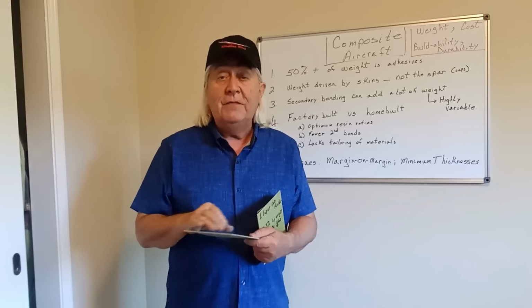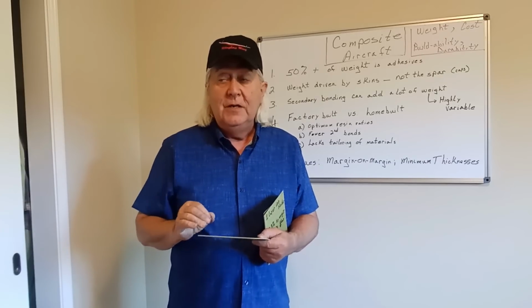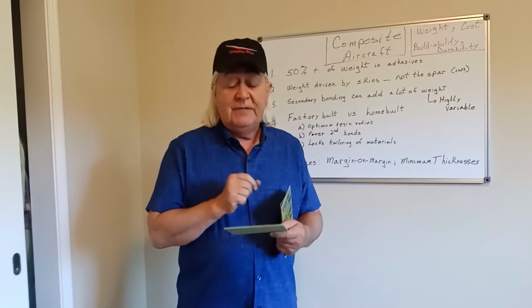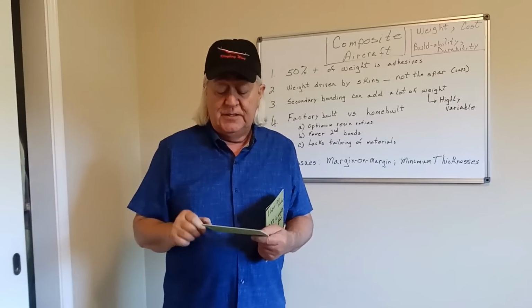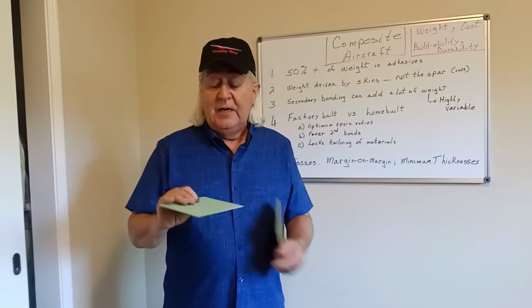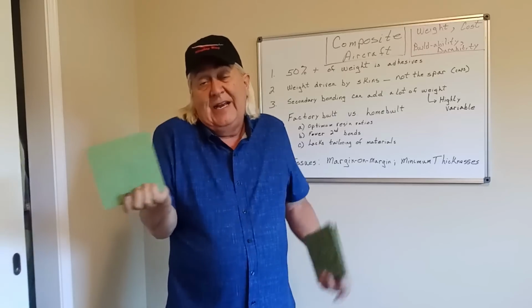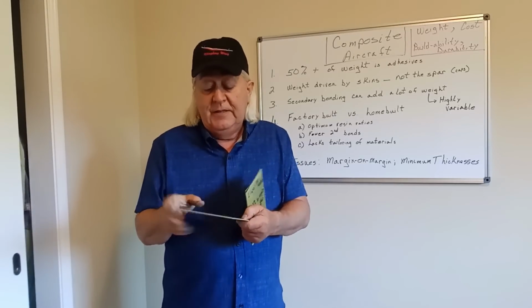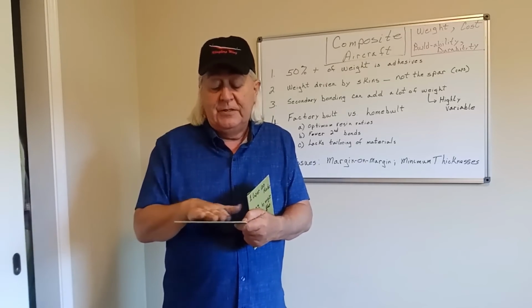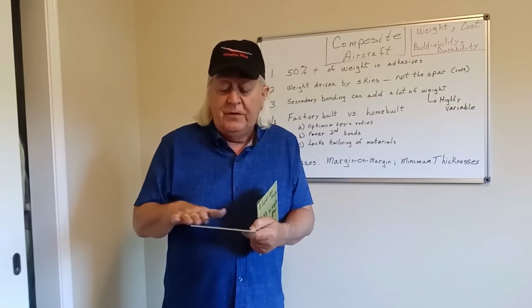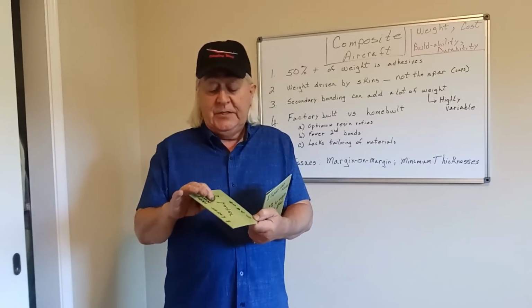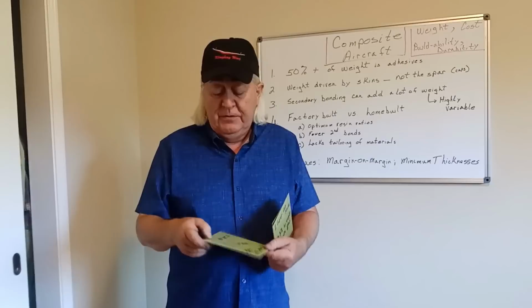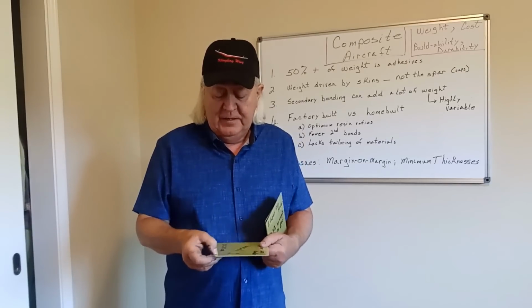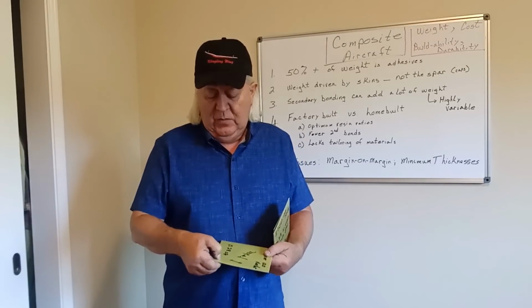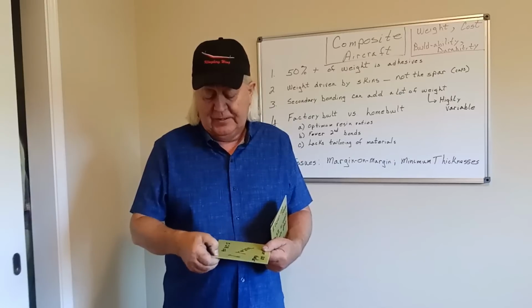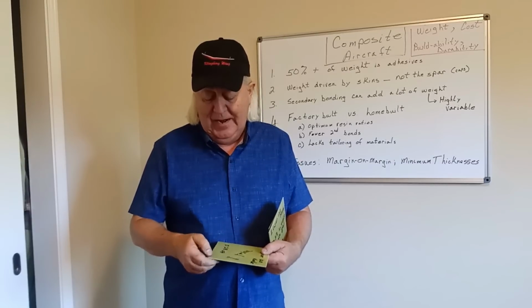And I laid up all of these essentially at the same time so that my hand was doing the same thing, using about the same amount of resin, and trying to be very careful about that. Now, I didn't bother putting any on the backside. It's kind of pointless. This gives us a good example of how much resin is going to go into the foam and what it comes out like. This is actually a pretty nice panel. And then I used my highly calibrated thumbnail to make dents in it. And I go, well, that's better than the fiberglass, but not much.